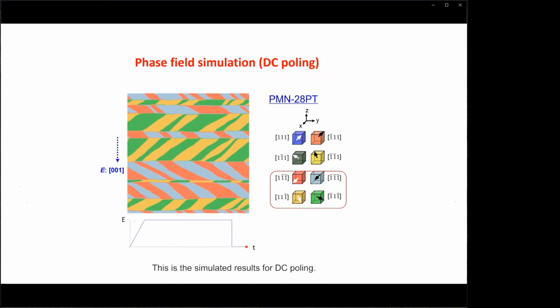This is the simulated result for DC poling. We can see that after poling along the 001 direction, only four electric-field-favored rhombohedral domains are present and formed a so-called 4R domain configuration. This is a 109-degree domain wall, and this is a 71-degree domain wall.